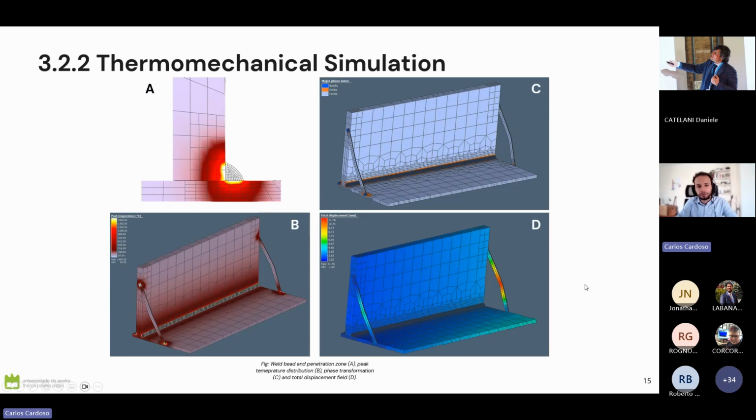So from the video, we saw that the thermomechanical simulation employed the coarser mesh, about 3,000 elements, which was necessary to manage processing time. And it took roughly 6 hours to complete, with the goal to see how the structure reacts mechanically, just like the bars deformation, but also what residual stresses and phase changes occur.